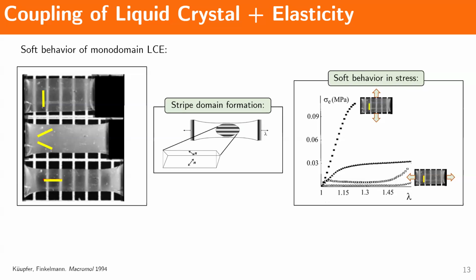So there's this interplay of length scales really, right? Where you have a microstructure formation and evolution. And then macroscopically, what you see is the soft behavior that happens, and also you see a change in your transparency of the material. So if your mesogens are all aligning in the same way, uniform way, then you get a transparent material. But if they're sort of like misaligned slightly, then you get this opaque material that happens. So these are all the studies that people have done on these monodomain LCE, right? And this change of opacity is a pretty good indication that you can see with your naked eye that there is this microstructure evolution and formation that happens in these materials.